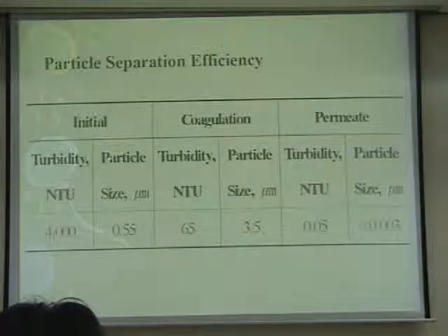And this was very favorable for the membrane system. In one case, we were able to decrease the particles, and the remaining particles were of bigger size, which were able to be captured by the microporous membrane filter. So as you can see, the final treated permeate water from the hybrid system had a turbidity of less than 0.5, which is of reusable quality, and the particle size was negligible, which suggests that 100% of the TiO2 particles were successfully recovered.